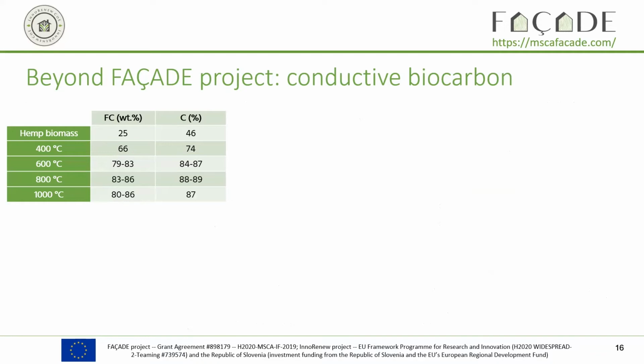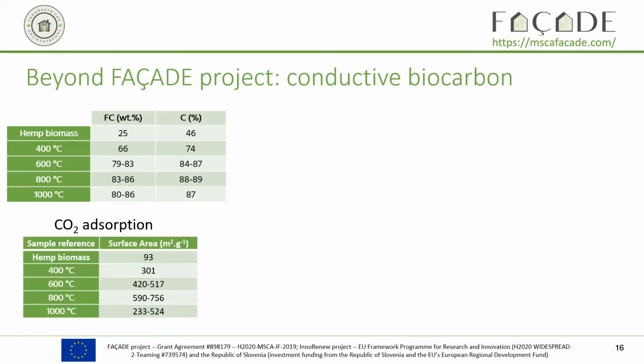First, we looked at the composition. You have fixed carbon and elemental carbon in the table here. And you see that from 600 degrees on, the fixed carbon and the carbon content are stabilized. So we cannot attribute the conductivity only to the carbon content in the biocarbon.